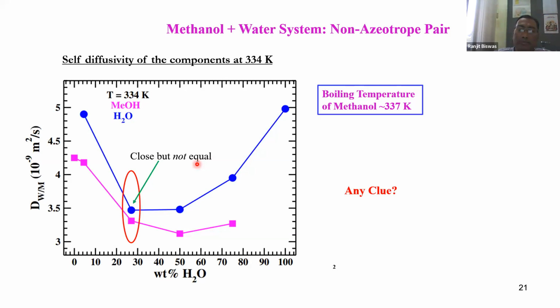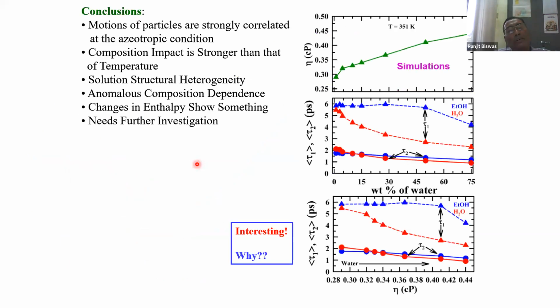So is this pretty general? For that, we need to study the propanol water system and many other systems to find out. And the conclusion is this: the motion of the particles is strongly correlated, but we still do not know how to understand that the viscosity goes up, but the reorientation times or the diffusion time scales actually become faster. And how that correlates with the hydrogen bond lifetime of the systems, particularly the structural hydrogen bond lifetime.